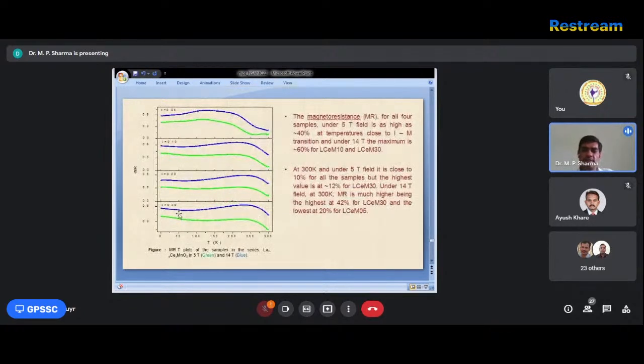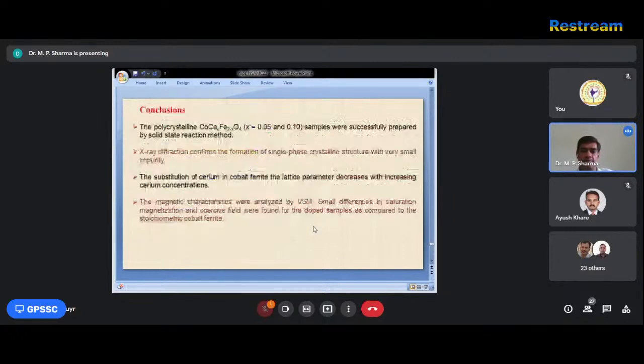So we have to calculate the MR at different fields. Magnetoresistance for all the samples has been considered, and the maximum is 40% at 5 Tesla and 60% at 14 Tesla. At 300 Kelvin and under 5 Tesla, it is close to 10%. At low temperature the MR is higher, while at room temperature it is lower, decreasing from 60 to 20% in the different samples. So now the conclusion.